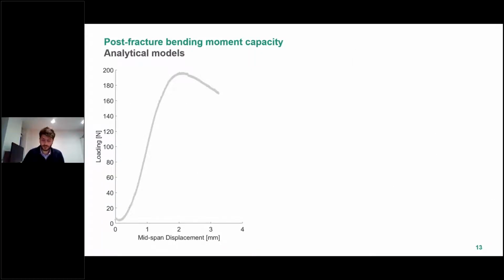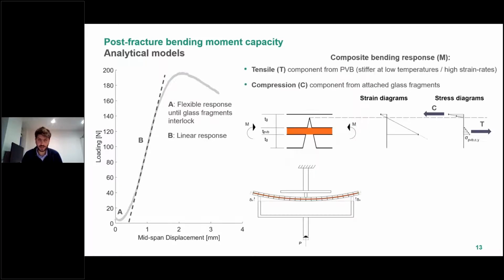Based on the experimental results from the low temperature bending test, analytical models were developed to describe the post-fracture bending moment capacity of laminated glass. Following the initial flexible response until the glass fragments interlock, a linear response is observed and the fractured panel bends elastically in a composite manner. At this stage, the PVB is in the initial slope of its stress strain diagram, and although it resembles an elastic material, it in fact remains viscoelastic.